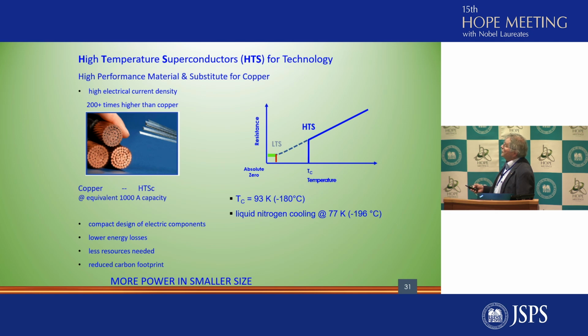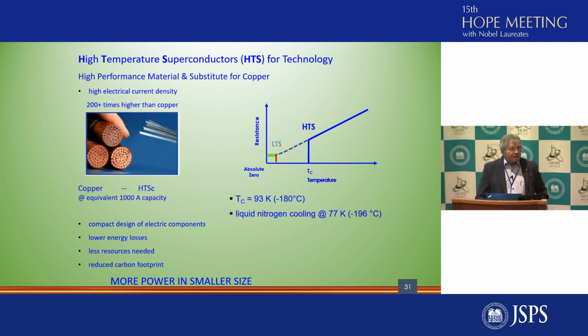This is a comparison between the amount of copper wires you need to transport 1,000 amps, and this is the ribbons of a superconducting composite, which has the same capacity. So what high-TC superconducting materials mean for the technology is you have more power in a smaller size. That means it is possible to have a compact design of electrical components, lower energy losses if you think of transporting energy from A to B. You need less resources, and you reduce the carbon footprint by this. Less resources mean also reduced carbon footprint.